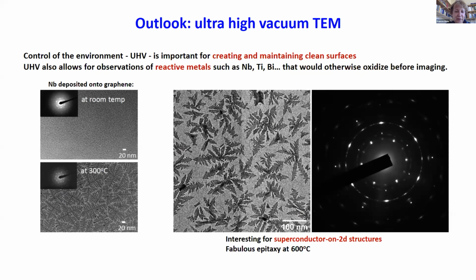So I think I've emphasized that you need to control the environment in order for these processes to work reliably and to get quantitative results out of them. We have to have a clean surface, we have to not have oxide, we have to not have contamination. If we achieve all those things, we can get very good epitaxy of materials that can be even quite difficult, like in this case, niobium deposited onto graphene, which gives fabulous epitaxy with these kinds of diffraction patterns. So we need an ultra-high vacuum environment in our microscope in order to do the growth experiments.